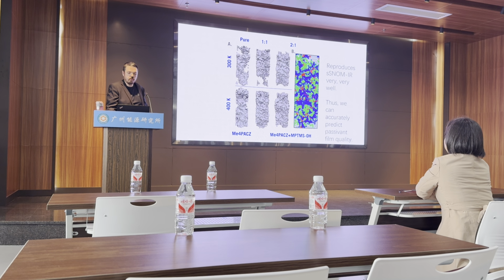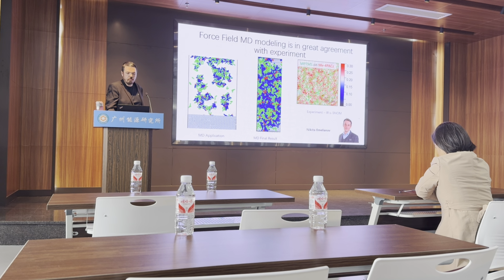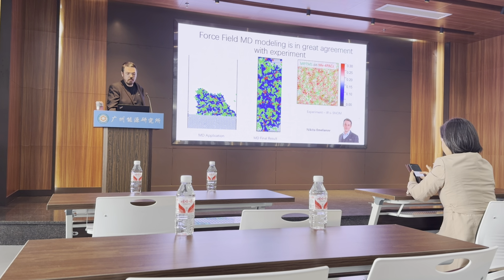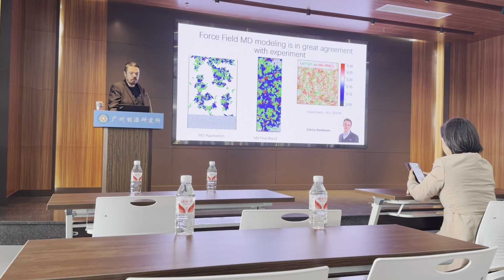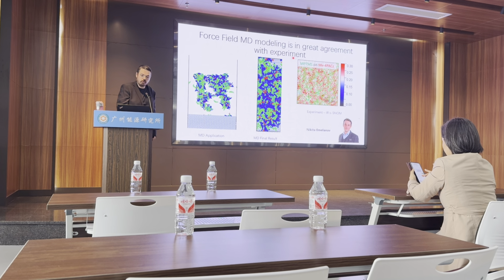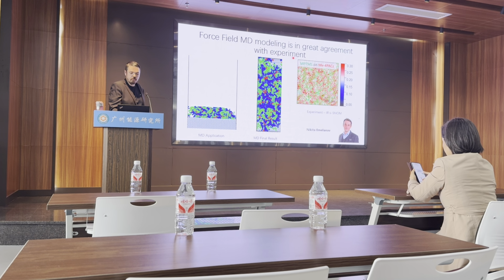This actually reproduces very well. So this is basically a heterogeneous kind of film that comes out. So we have Mo4PACZ and MPTMS not mixing, but kind of forming separate phases. And that's actually what, if you imagine the red being blue, we can compare them, and that's actually what we see in the experiment. So this was done after our simulations. So the simulations predicted the experiment, and that's the golden standard, I think, for theory, if they can predict something new before it's done.